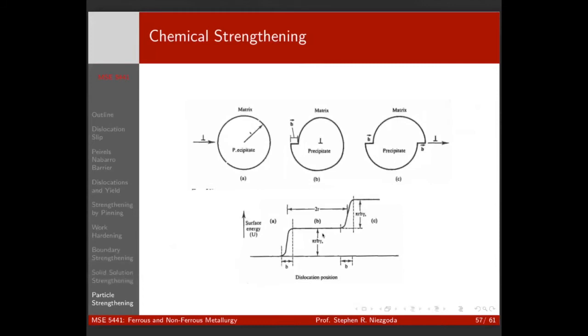So chemical strengthening is another effect, and this is generally pretty small, at least if only one dislocation goes through, right? Or if the particle is very large. Because when the dislocation goes through, we shear our particle and we make a step which is now new interface, right? So there's an energy penalty that has to be paid, right? The surface energy per unit area of interface. So by cutting this, we're making new interface. We have an energy cost associated with this. So if the particle is very large, the amount that we're increasing the surface area is very, very small, right? So it's kind of negligible. But if this is a very small particle, say tens of Burgers vectors across, like say GP zones in aluminum that we're going to be talking about, this can be a pretty big effect.